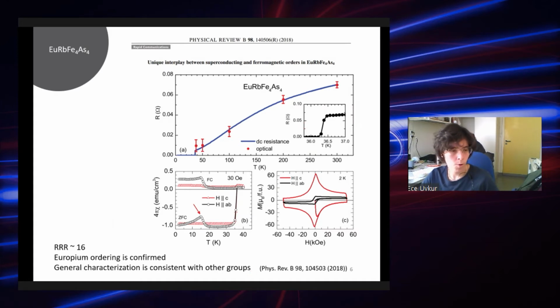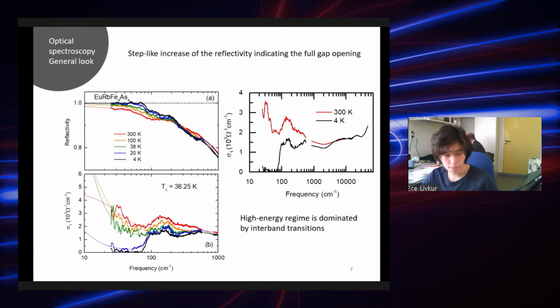The samples were quite small though, well, maybe less than 0.5 millimeter, which by optical spectroscopy standards is quite small. Therefore, you see a lot of wiggles in the spectrum, which we didn't like too much.